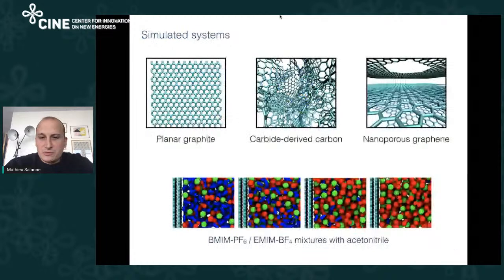So in this work, I will mostly talk about 3 types of materials. The first one is a baseline. It's planar graphite, and in fact, it helps us to have a benchmark because it's the simplest system you can study. And then to understand the effect of porosity, we have 2 types of carbon. The first one is carbide-derived, so it's very disordered like you see here, but with a very strong porosity, with pores less than 1 nanometer in size. And then we also studied more ordered structures like the nanoporous graphene that you see on the right to see whether the order or disorder of the structure is playing an important role.